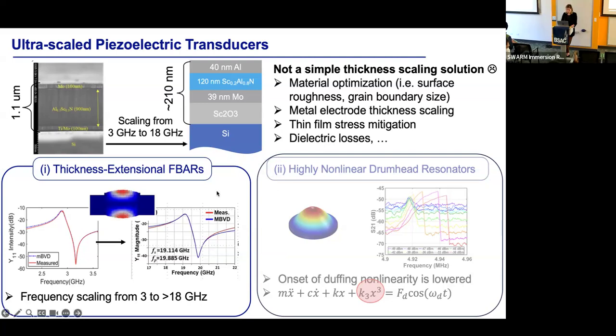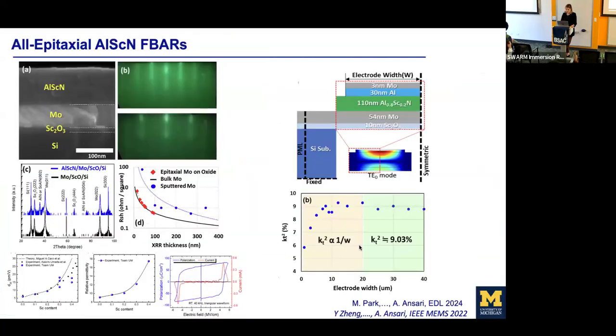So for this, we partnered with two groups, one with the University of Michigan, which are MBE growers of III-nitride materials, with the goal to build very thin layers of aluminum scandium nitride grown on a molybdenum bottom electrode, and then released again through the silicon substrate. So here we're showing that very good material properties could be achieved, and the sheet resistance of the epitaxially grown moly, this was done at IQE, which is a semiconductor manufacturing company. We could measure sheet resistances comparable to bulk molybdenum, because we were using single crystalline epitaxial moly as opposed to sputtered moly.